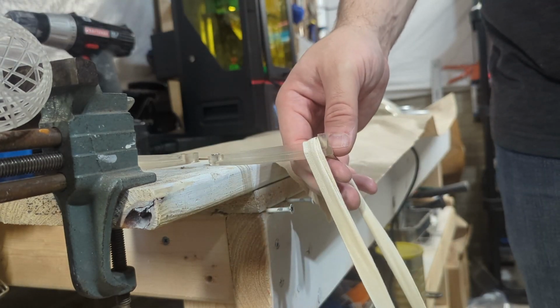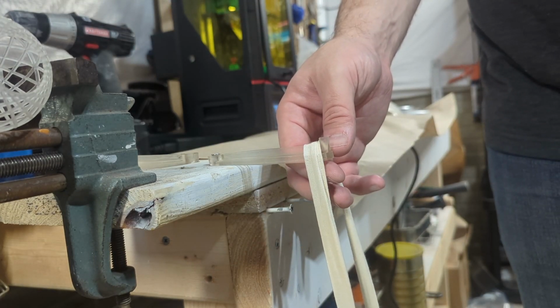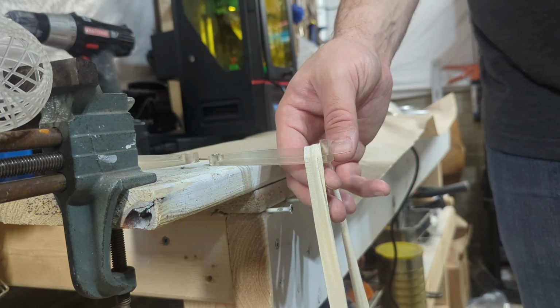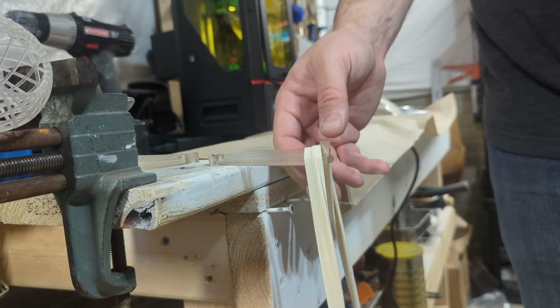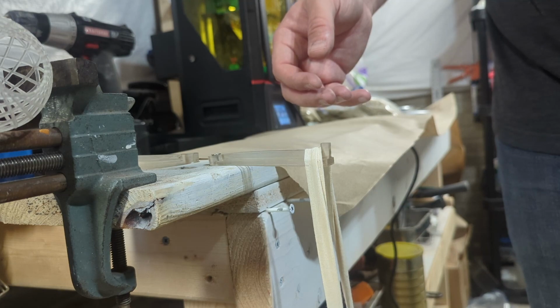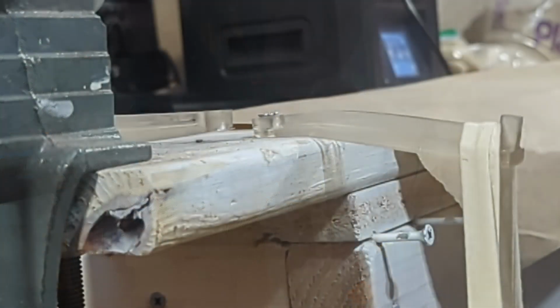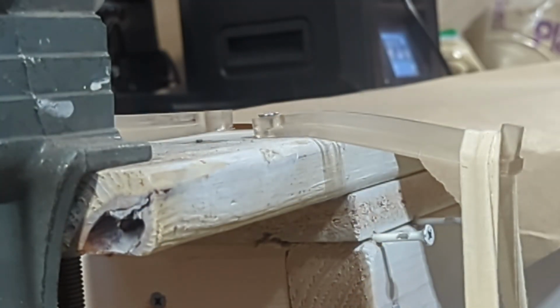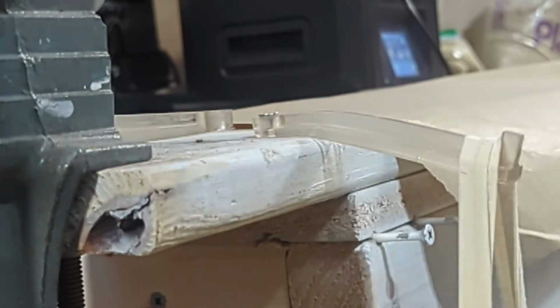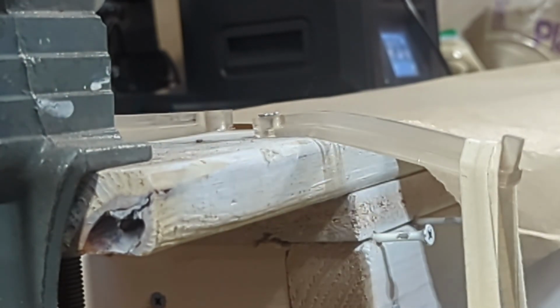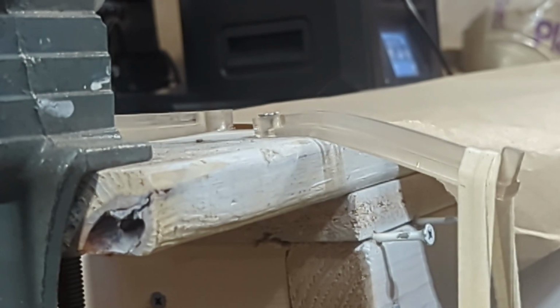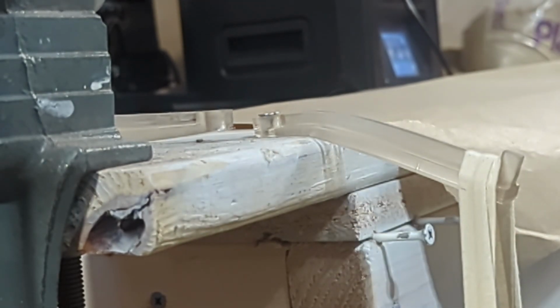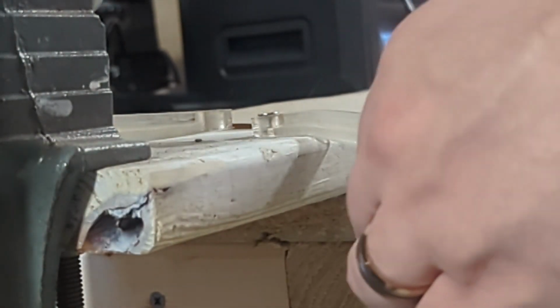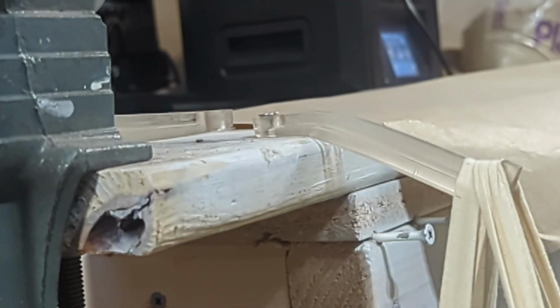I left these 15 pounds here for about 25 minutes on three separate tests and did not see any significant deformation after the initial bending. So I wanted to see how much weight it would actually take to finally snap these. And I ended up using a large amount of the sand that I had on hand, and around 30 pounds is where we had our catastrophic failure.